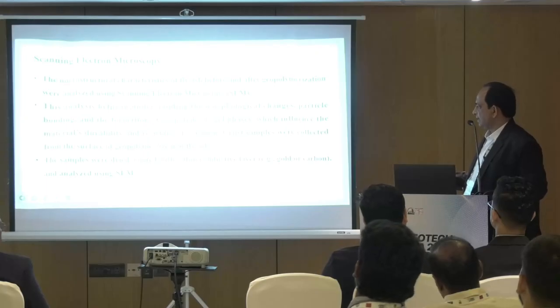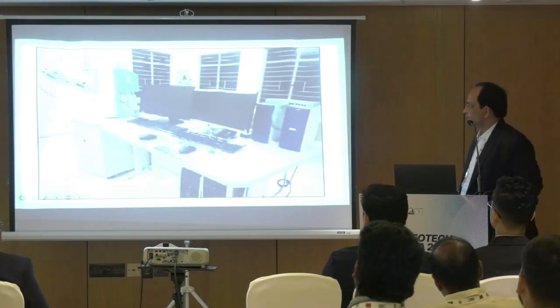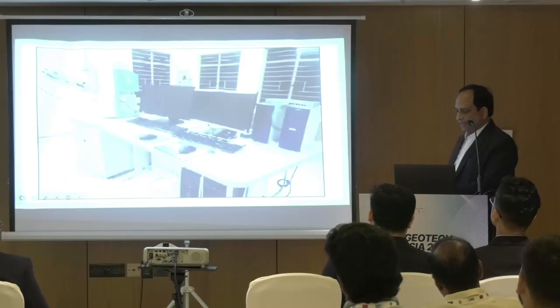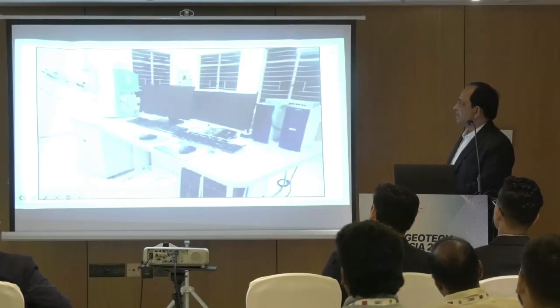Then just to know the microstructure of it, we have gone for the SEM test, just to understand the morphological changes, whatever the bonding we had and the formation of what type of gels that are laid, which is influencing the material durability along with resistance to erosion. Of course, the crust samples were collected from the surface of geopolymer treated fly ash, and we had different coatings of this also. This is the SEM test setup we have along with the EDS unit in the CSRS lab